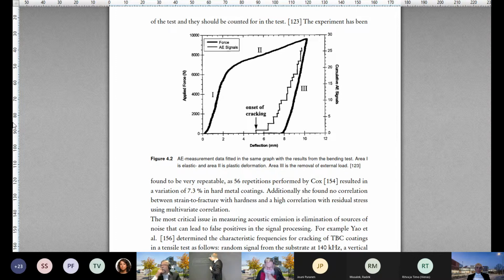Afterwards, the macro crack, I would think, is once these join and you have a true crack that you could actually see, probably not really, but you could easily hear it when bending. So these would probably be midway from the onset of cracking to the finish line. And you would start to have more and more of these. At some point, once the crack comes here, it either stops, or if the cohesion is higher than the adhesion, the crack could start to propagate between the substrate and the coating.